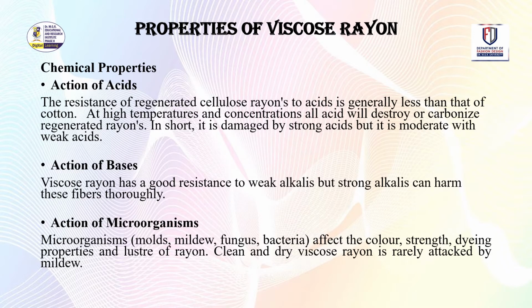Chemical properties. Action of acids. The resistance of regenerated cellulose rayon to acids is generally less than that of cotton. At high temperature and concentration, all acids will destroy or carbonize regenerated rayons. In short, it is damaged by strong acid, but it is moderate with weak acid. Action of bases. Viscose rayon has a good resistance to weak alkalis, but strong alkalis can harm these fibers thoroughly. Action of microorganisms. Microorganisms affect the color, strength, dyeing properties, and luster of rayon. Clean and dry viscose rayon is rarely attacked by mildews.